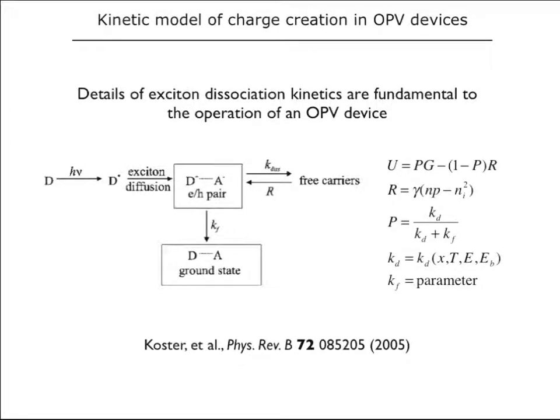Well, we use a kinetic model and try to understand all of the rate constants between the different states of the device. So a relatively simple version of it is that we start with a material like the donor, which we excite to form the exciton. Then we form this charge transfer state, that intermediate charge sharing between the two materials. And then there is generation of free carriers, hopefully. Now this process can go backwards through recombination, or we can get ground state recombination that is a removal of energy from the system. So this model was published initially by Koster about 6 years ago. And by fitting a variety of parameters, we can get a pretty good estimate of what the ultimate charge generation of free carriers is out of the device.